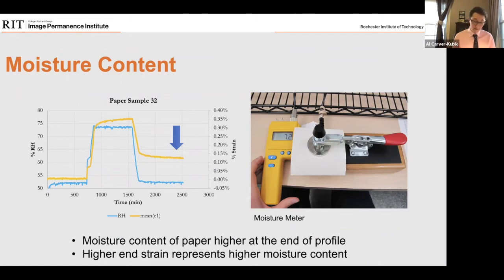And this is consistent with the results from our storage environment research, in which we have found that moisture desorption is slower than absorption. So again, we just have to let it stay at 50% for a really long time to drive off the rest of that water that we put into it. Another way you can do it is you can actually increase the temperature slightly, and an increase in temperature will push some water out of it, and then that will sort of bring the strain back down or remove some of the water.